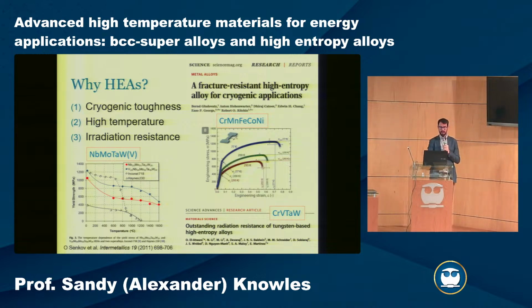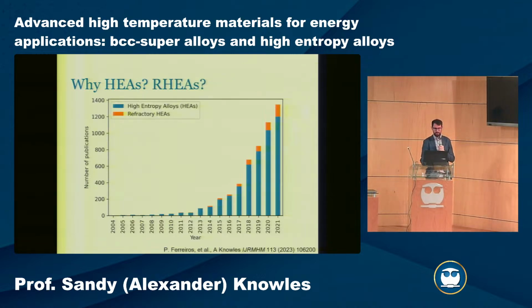So this is, again, an article from Science Advances just a few years ago, where we're seeing very, very little irradiation hardening. So in terms of the irradiation resistance of high entropy alloys, there's something about when you mix the elements together in this complex way that you get massively improved properties some of the time. It's not a guarantee, so not all high entropy alloys are fantastic. Some of them are terrible, but some of them show this kind of behavior that really doesn't exist in other materials. And if we can understand the mechanisms for that, it can really help us design new materials. So this has become a huge, huge area internationally.